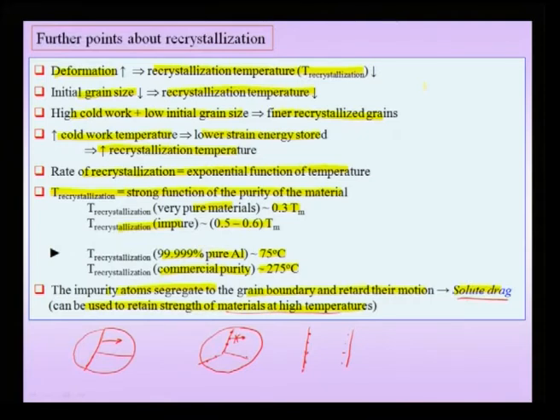So, let us try to summarize this slide: what are the factors which affect recrystallization? We are worried about the amount of deformation, or the recrystallization temperature in particular. So, we are worried about the amount of deformation I have caused to the material. At what temperature did I cause this deformation? In other words, how much of the energy I input actually is stored in the microstructure in the form of defects. We have noted that the higher the deformation or the higher the energy stored, the lower will be the recrystallization temperature. Additionally, we have noted that it is a function of the purity of the material.